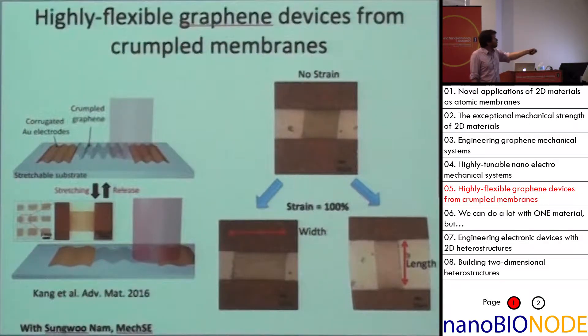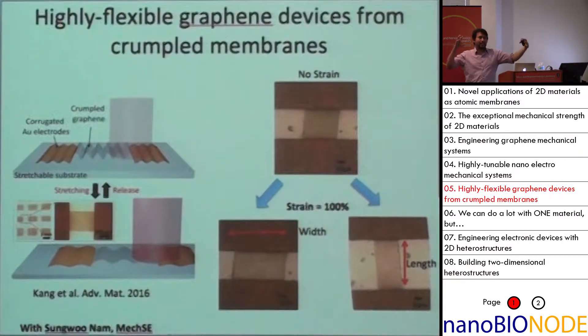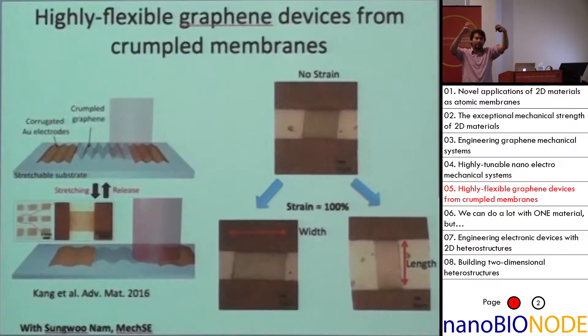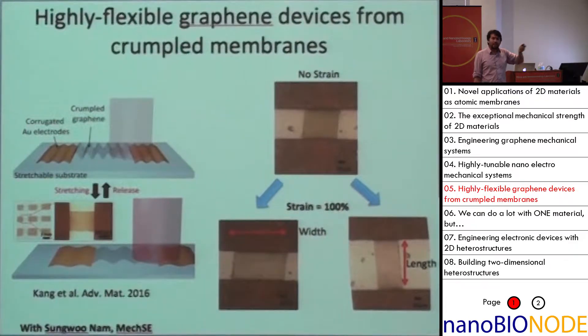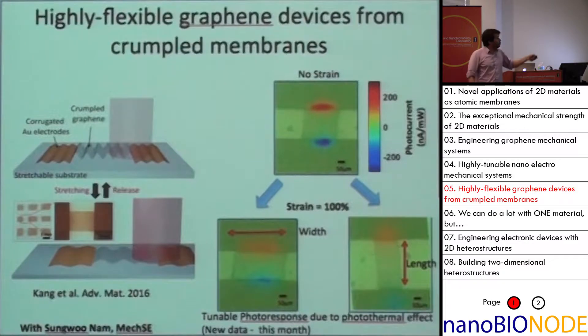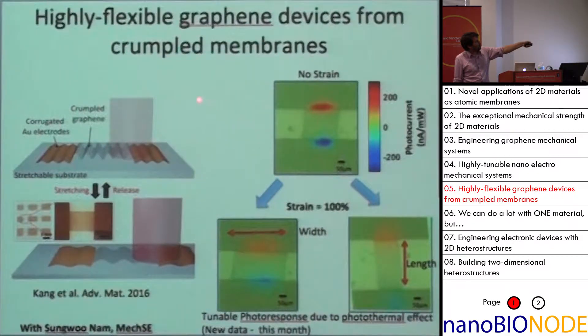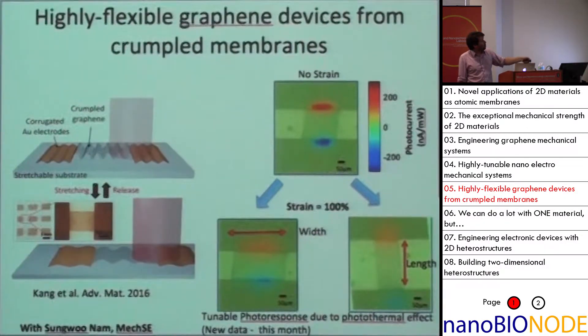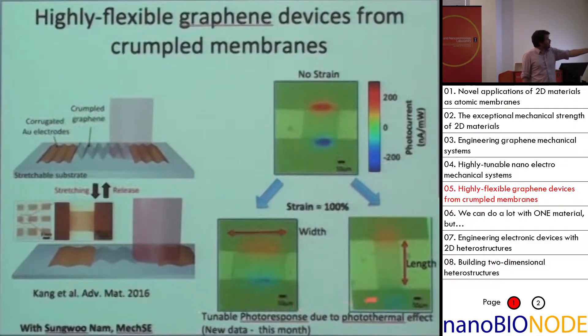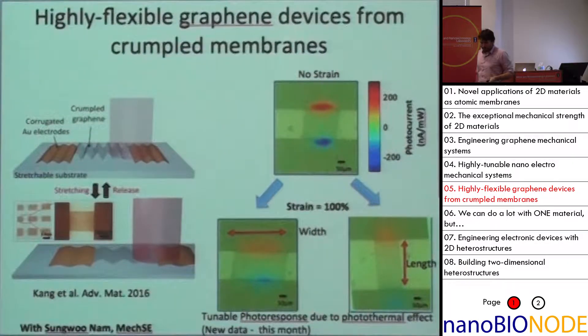In a totally different realm, this is a very recent project where we have collaborators making crumpled graphene devices. They can crumple the graphene and then build a device on it. You can stretch and retract it by 100% without it breaking. They noticed when they shined light on it, they got a photo response. So we built a scanning photocurrent setup to map out the photo response as a function of position. We can see the photo response in graphene membranes right at the electrodes. As we stretch the crumpled graphene, the area of photo response moves and changes in intensity. The photo response appears to come from a photothermal effect.